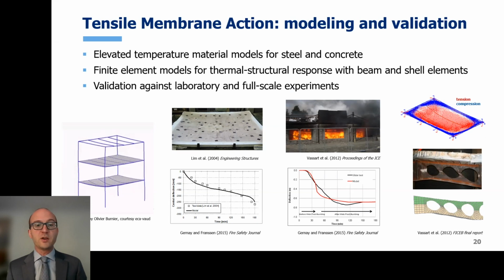One of the modeling challenges was notably to develop appropriate models for the materials, for the concrete, which is something we discussed, in order to capture possible failure modes in the concrete slab. We discussed it with the example of advanced high-strength steel, but similar efforts were needed for concrete in this case. On the slide, you see displacement-time curves obtained with the software SAFIR when modeling a laboratory test conducted in New Zealand and a large-scale test, the one shown previously in Northern Ireland. Good agreement was achieved between the model and experiment.